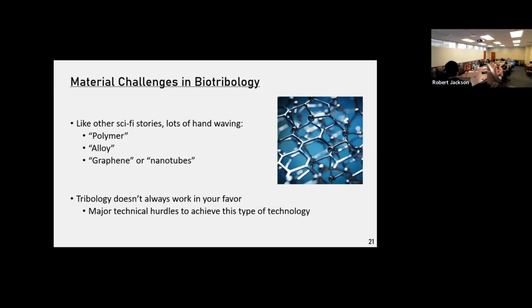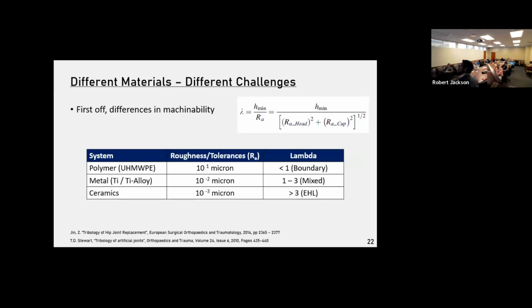When you're a material scientist, you have to figure out there are always limitations, and not just by virtue of something being a polymer or an alloy does it make it high performance or special. It's really about the material and the application selection. So you've got different materials and different challenges. In prosthetic hip and joint replacements, you've got really three areas. You've got polymers, traditionally ultra high molecular weight polyethylene; metals like titanium and titanium alloys or surface treated titaniums; and then ceramics, things like hydroxyapatite that can mimic the natural structure of bone or bone marrow, and you can implant cells and things into.